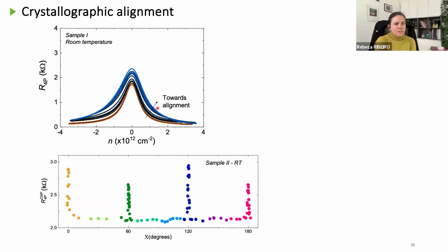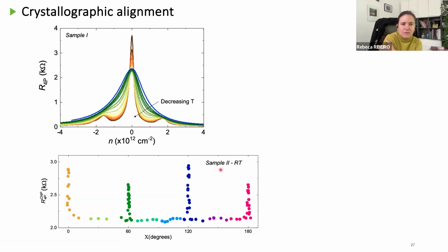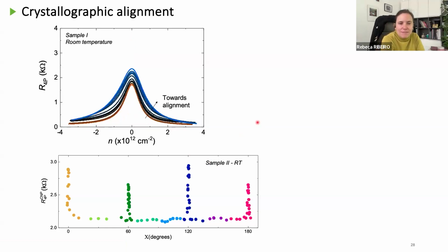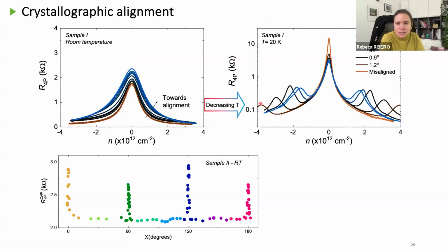So to confirm this, first, we took the largest peak, and we went to low temperatures to see if we really are aligned at this position. We could observe the presence of the satellite peaks, the same satellite peaks that we were talking about before. So good news, we are aligned. That's already something. Now, if we do the same for several of them, we can see the peak moving, which reflects that we are really changing the alignment. I mean that in these strong peaks, we are really getting close to alignment. So, okay, we are getting to alignment.